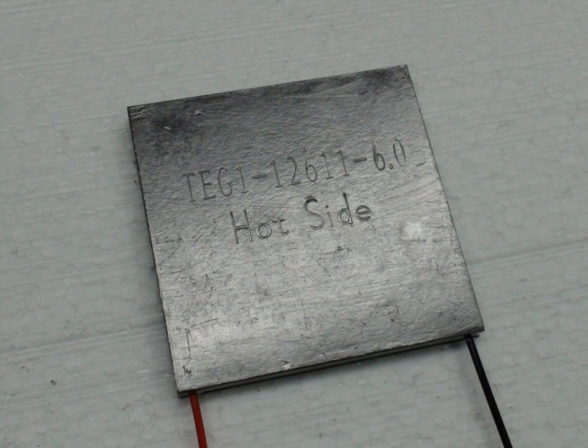New materials. Researchers are trying to develop new thermoelectric materials for power generation by improving the figure of merit ZT. One example of these materials is the semiconductor compound zinc antimonide, which possesses an exceptionally low thermal conductivity and exhibits a maximum ZT of 1.3 at a temperature of 670 K. This material is also relatively inexpensive and stable up to this temperature in a vacuum, and can be a good alternative in the temperature range between materials based on bismuth telluride, Bi2Te3, and lead telluride, PbTe.